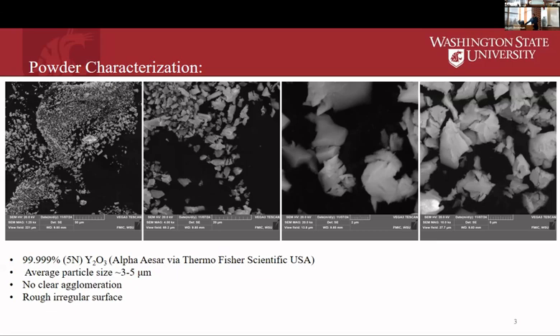What we found was that the particles we were using have a very rough surface with a lot of fracture edges, most likely from the way it was manufactured and processed. It was probably milled down to this particle size, so the very irregular geometry ended up posing some problems we'll get into later. The other important thing here is because it's a large powder, and was most likely milled instead of chemically synthesized, there's a very low degree of agglomeration in the powder. It doesn't tend to really join with itself—it's a lot of diffuse particles instead of a few larger or many small particles combined into singular larger particles.